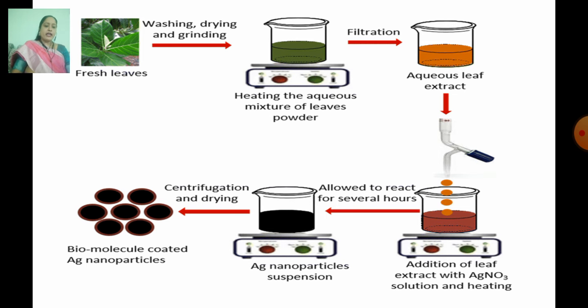Here we have taken the Artocarpus heterophyllus leaves, that is nothing but jackfruit, which all of you know. I have taken the leaves, then washed, dried and ground them, then heated the aqueous mixture of leaf powder, then filtered it, and the aqueous leaf extract is obtained. Then this leaf extract is added to the silver nitrate solution, and then we heat it, and we get a change in the color of the solution. See, the color of the solution is changed from reddish brown to blackish, and there is a formation of silver nanoparticles here.